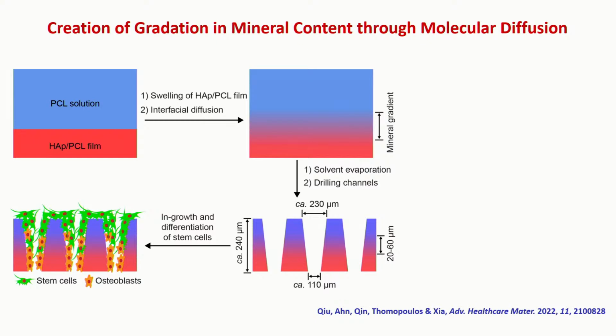That basically allows us to control the differentiation of stem cells you seeded onto the surface of these channels. And this kind of fabrication technique has another advantage actually. If you look at the cross section of these channels, it's not like straight walls. They are going to have this particular funnel shape. This is going to be unique when we apply this between tendon and the bone. They can form interdigitated tissue structures that can further enhance the mechanical strength of the repair.